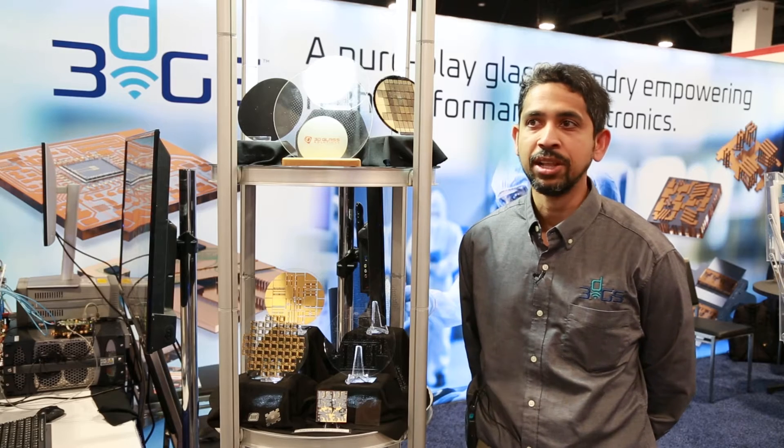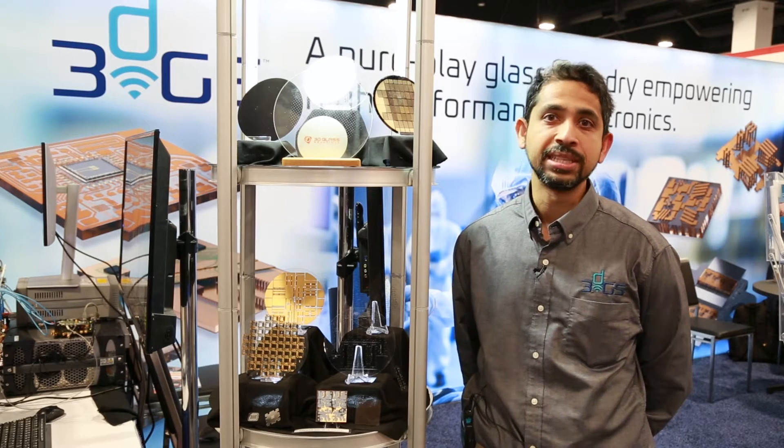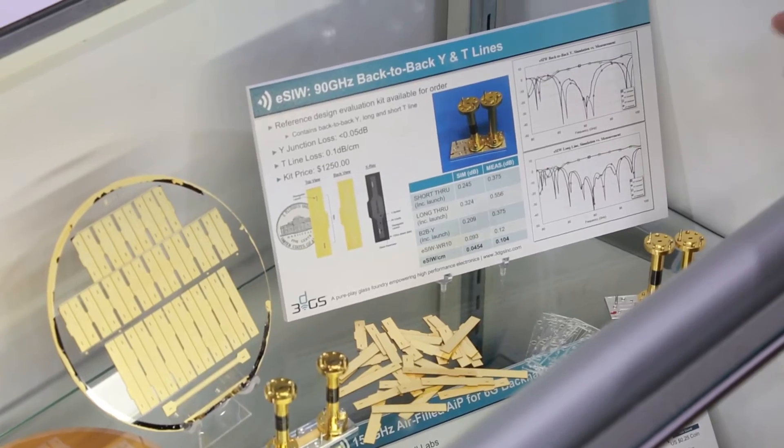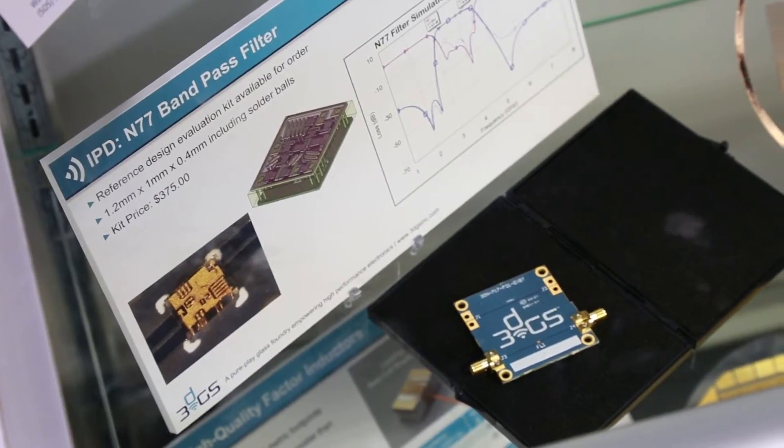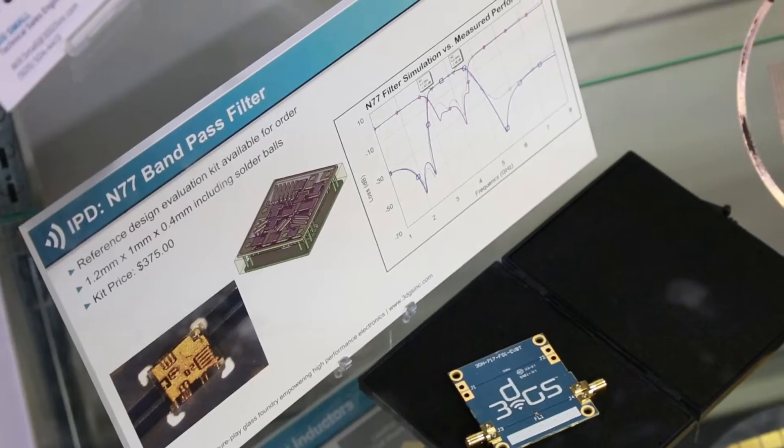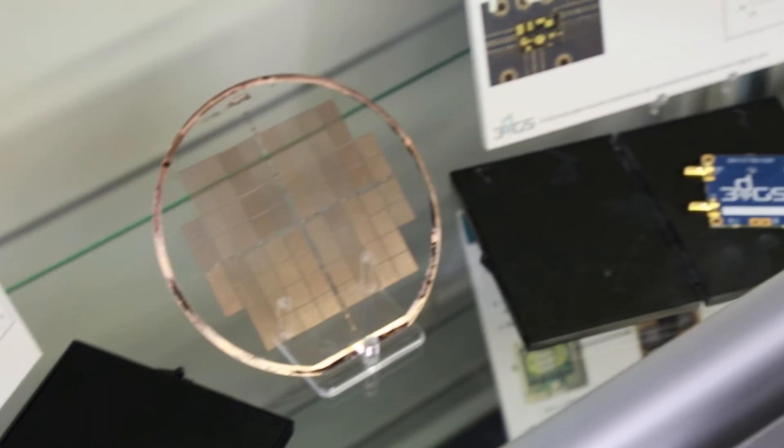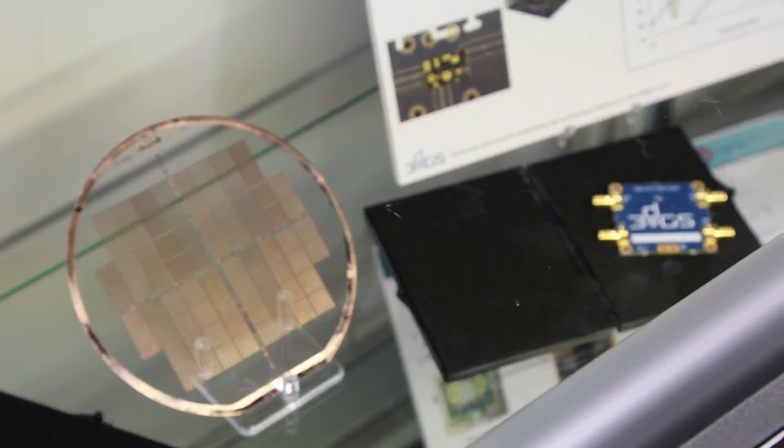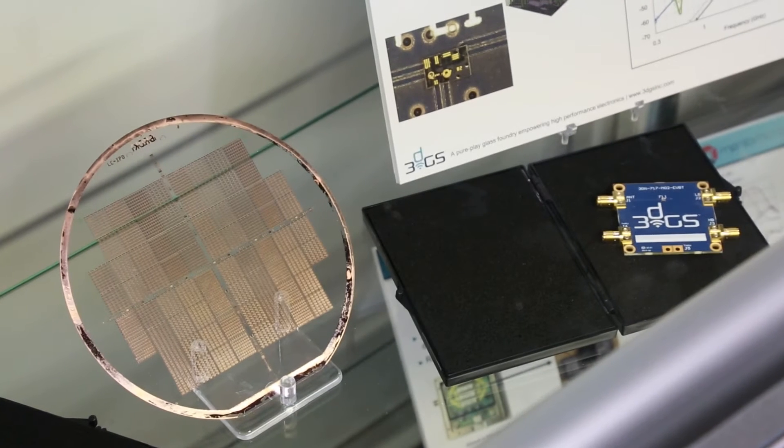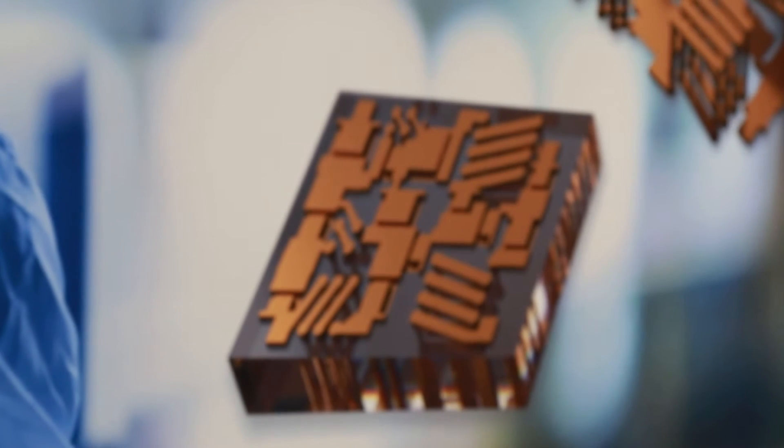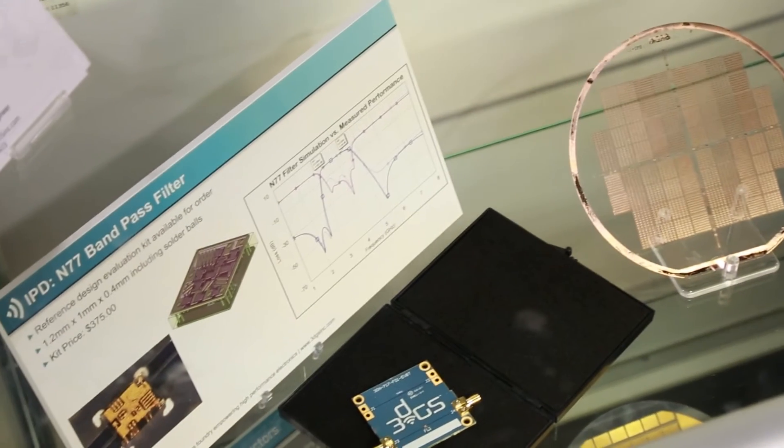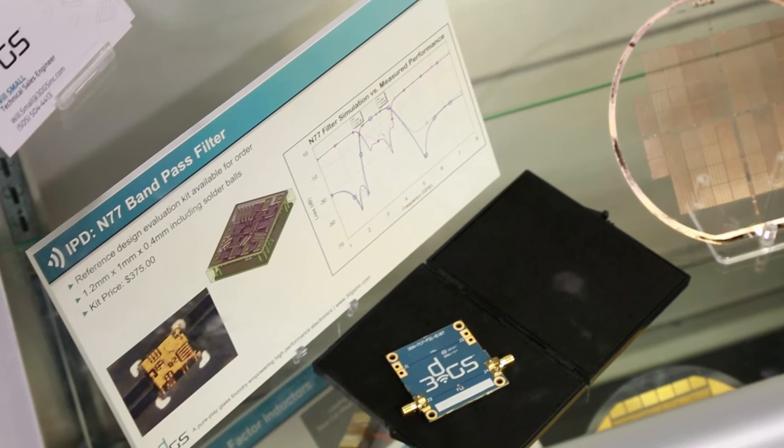What's cool about 3D glass is that we make electrical circuits in glass. We can get very tight tolerances and make very accurate vias—40 micron vias in a 300 micron thick wafer. Our process uses photosensitive glass, so whether it's a single via or...